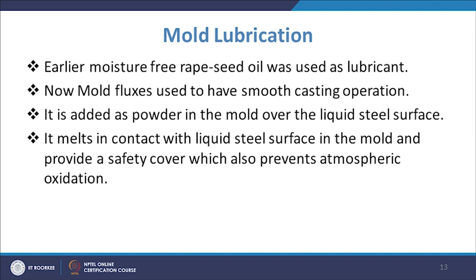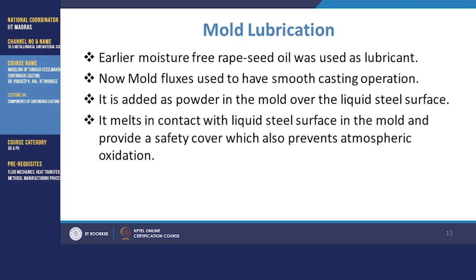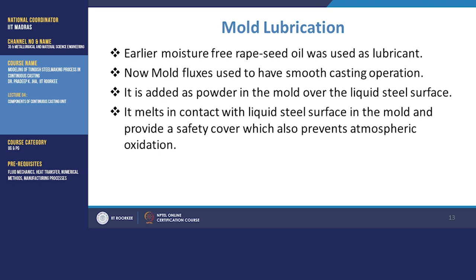Mold lubrication. Earlier, moisture free rapeseed oil was used as the mold lubrication, as we had discussed, that you have to have some lubrication so that there is no sticking. Now, mold fluxes are used to have the smooth casting operation, and they are added as powder in the mold over the liquid steel surface. That is the normal practice: you have a powder given at the surface, and when it comes in contact with the liquid surface, it melts and goes in between the mold wall, so there will be a layer of that lubricant, and that will ensure that there is no sticking of the surface. Another advantage is that it prevents oxidation from atmospheric air. This is an example of these mold flux powders.